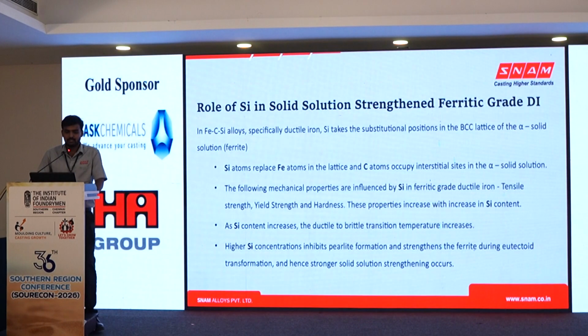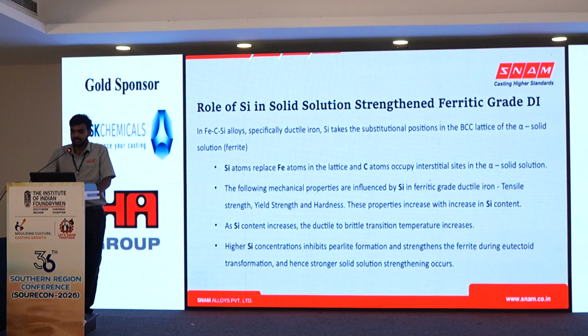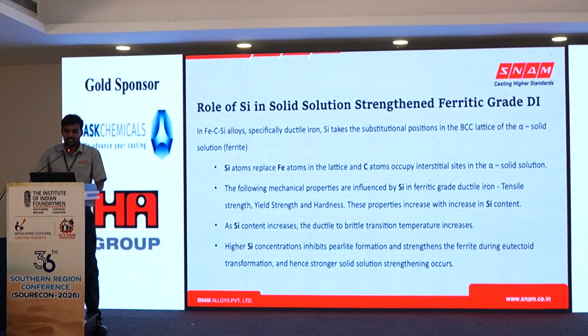So, the role of silicon in solid solution strengthened ferritic ductile iron. In Fe-Si alloys, the silicon acts as a substitutional solid solution. Silicon atoms replace the iron atoms in the BCC lattice, and carbon atoms occupy the interstitial sites in a ferritic solid solution. As I told, mechanical properties are majorly influenced by silicon. With increasing silicon percentage, the overall mechanical properties will increase.